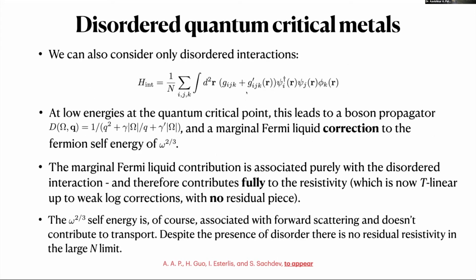And one can also eliminate the V term and consider only disordered interactions of this kind. And then because you still have this clean part that dominates the fermion self-energy, you get omega to the 2/3 fermion self-energy. But the disordered interaction leads to a marginal Fermi liquid correction to this omega to the 2/3. And since the omega to the 2/3 comes from forward scattering, but the correction does not, when you look at the transport properties in this theory and sum up all the vertex corrections in the large N limit, there is no T to the 2/3 resistivity. Rather, your resistivity just comes from marginal Fermi liquid correction, and you get a T linear resistivity. And because the disorder is coupling to a higher order interaction operator and not the potential operator, there's no residual resistivity, even though this is disordered within the large N limit.